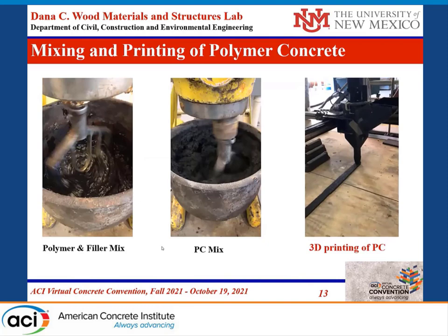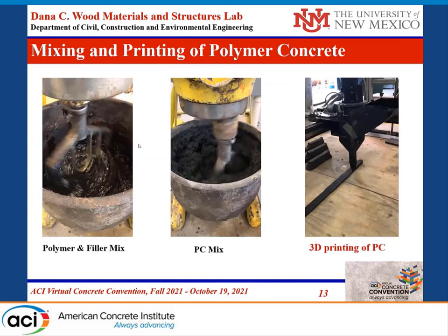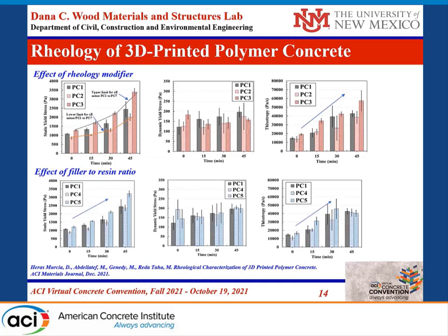We ran different mixes and 3D printed the polymer concrete material to make samples for mechanical property testing. Looking at the effects of rheology modifiers: they have a significant effect on static yield stress, very little effect on dynamic yield stress, but a big effect on thixotropy — which is critical for 3D printing buildability. We also see effects of filler-to-resin ratio on static yield stress and thixotropy, with the objective of selecting an optimal mix for large-scale printing.